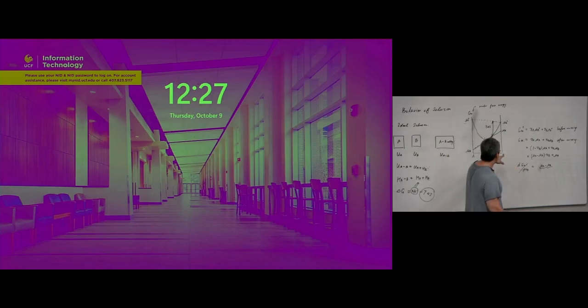Follow this one, and you can see that the intersection on the A axis is mu A, on the B axis is mu B. So it all follows this equation, correct? So that means if we know the xB, or the fraction of B atoms inside the alloy, and we know this G chart, then we just need to do a tangent line across this chart. And the intersections on the A and the B axes indicate the chemical potential of A and B in the mixture. And you can see the mu A is different from mu A naught, and the mu B is different from mu B naught. That means their chemical potential also drops.